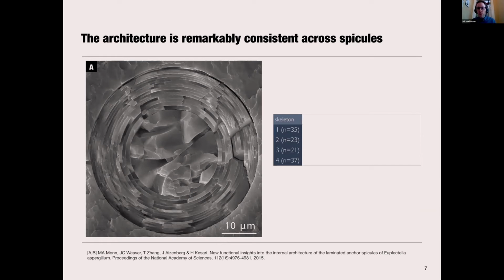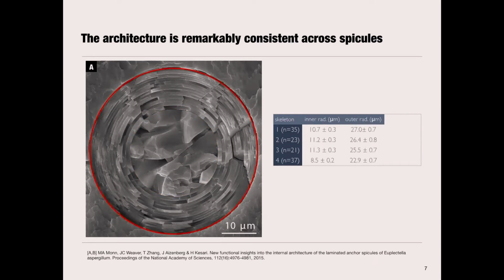So early on, what interested us very much in this structure, in this animal, is that if you look at a number of spicules from a number of different individuals from this sponge, this is showing 4 different individuals, 4 skeletons, and a number of spicules, n equals 35, 23, 21, 37 from each skeleton. We measured the inner radius, that is the radius of the core, the outer radius, or the radius of the outside of the spicule, and the number of layers in the spicule.